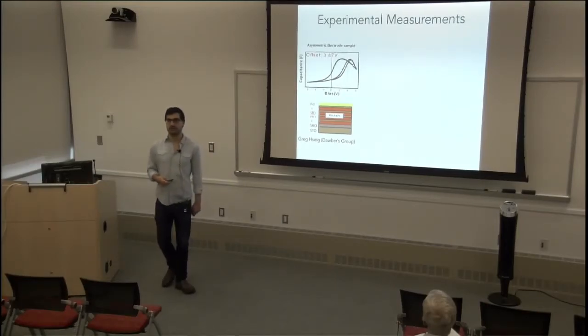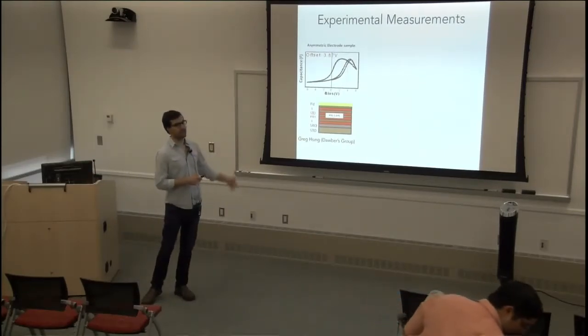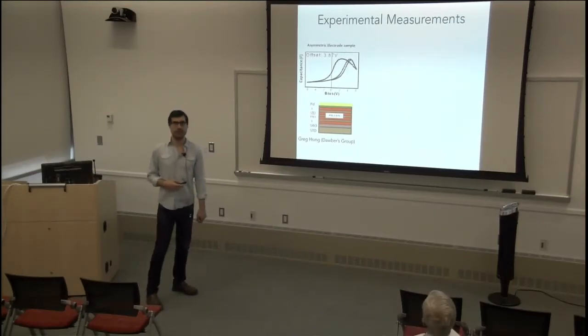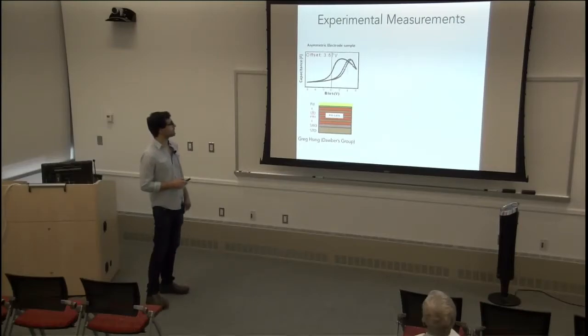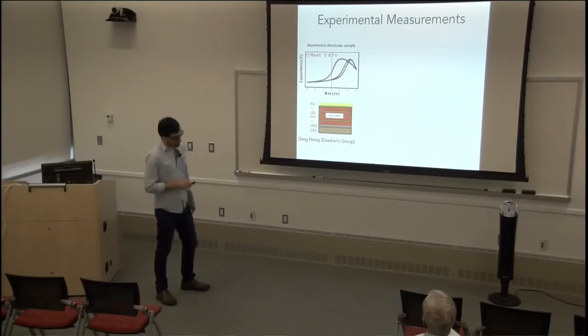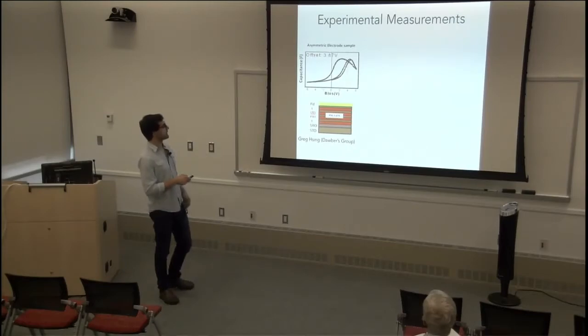But so you see a displacement from the center, and initially this didn't really bother the experimentalists because this type of displacement has been known for years and years. Historically, what's been blamed for this displacement is the fact that you have asymmetric electrodes. Here in the bottom you have a strontium ruthenate electrode, and on the top you have a palladium electrode. The fact that you have two different electrodes messes up your electrical measurements and gives you this type of bias offset.